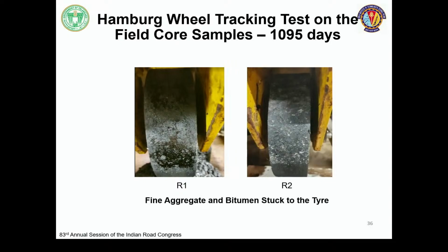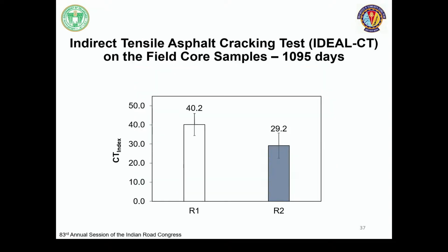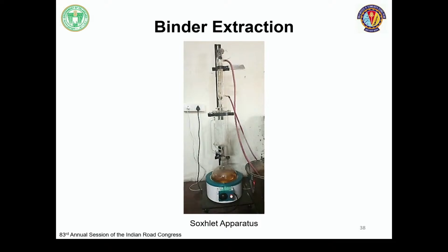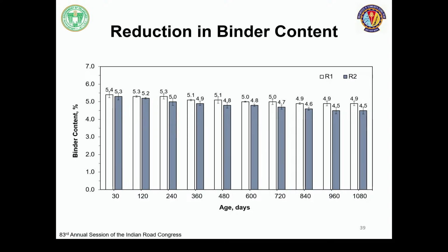So every bad thing also has an advantage. Because of this aging, the rutting did not increase, but there was a potential for cracking. So then we tried to extract the bitumen and test the bitumen. There was one thing observed.